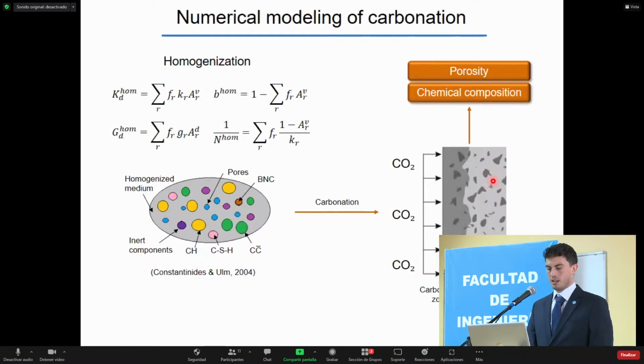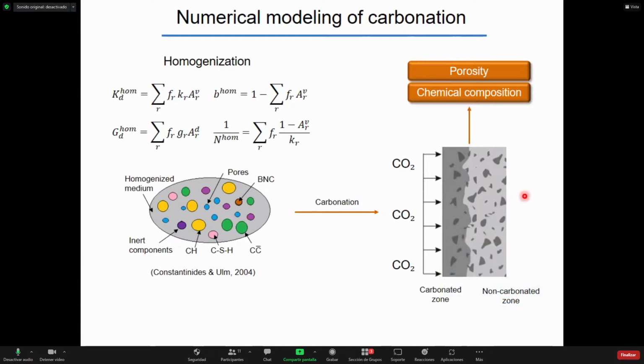For this, the model uses a homogenization tool to consider the contribution of each cement component. The overall stiffness of the material will be the sum of each component's property. And when we carbonate this material, we will see that the chemical composition and porosity are modified, and as well the considered media will be modified over time.